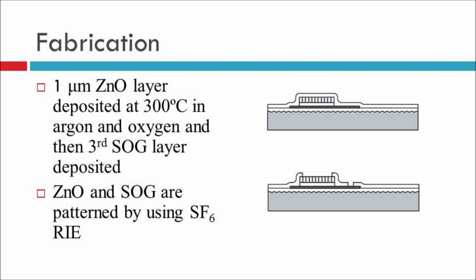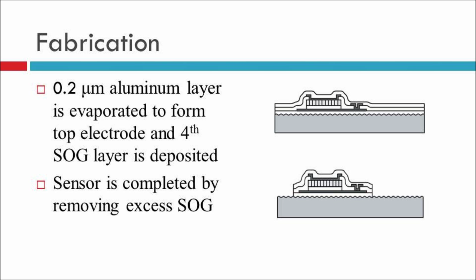Next, we can deposit our zinc oxide layer of 1 micron. This is done at 300 degrees in argon and oxygen, and then after that, a third SOG layer is deposited. The zinc oxide and SOG layers can then be patterned using an SF6 reactive ion etching process. Finally, the top electrode is evaporated on, and then another SOG layer is deposited on top of that. The sensor can be completed by removing the excess SOG.